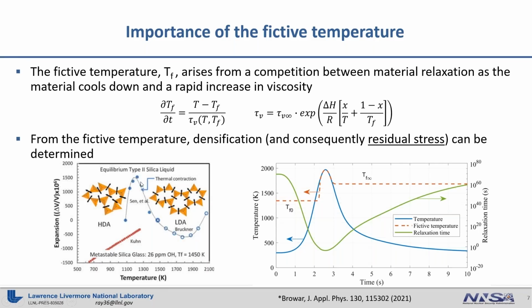And if you continue heating it, the fused silica kind of reorients itself into those rings, as you see there above the LDA, right there. And if you heat it up more, those start to kind of collapse on themselves. And that phenomenon is called densification. And so if you, right where that mouse is pointing, if you get there and then you cut off the heat source, there's going to be a competition between material relaxation, which would love to go back to that equilibrium state, and the viscosity, which is going to be increasing now that the heat source is off.